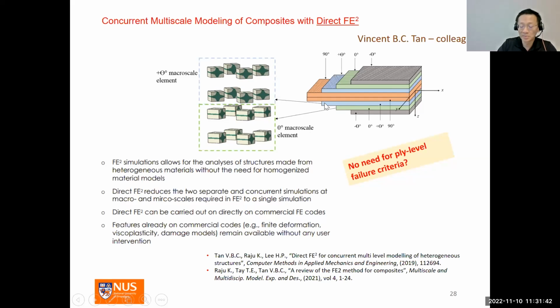And so for example, the top ply here would have the Gauss points. These are the RVEs, the simple RVEs with the fibers and the matrix at the Gauss points. So the magic sauce of the direct FE squared is that by scaling the volume of the RVEs, that's found by Vincent, to ensure energy equivalence between the RVEs and the macro elements, we can show that with minimal Python coding, we can use direct FE squared in a commercial FE software such as Abaqus.